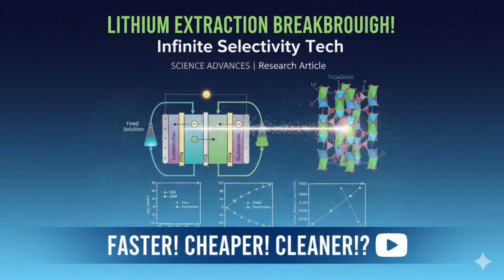Okay. Then there's electrochemical intercalation. I've heard that mentioned. Sounds a bit like how a battery works. It is conceptually similar, yeah. Using electrode materials that selectively pull lithium ions in. And it can be quite selective for lithium, which is promising. There's always a but. The main issues there tend to be electrode lifespan. They can degrade over time. And the fact that it operates in semi-batch modes. You fill it up, extract, empty it, repeat. Not really ideal for a continuous, large-scale industrial process. Right, you want something that just keeps running.